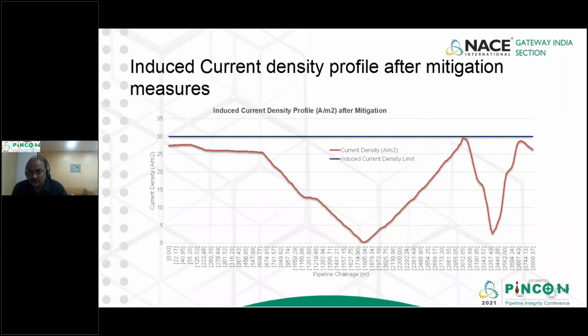So we then gave clearance for putting gas into the pipeline, because many big customers were there in this pipeline, and we were not able to commission them because we had this issue of AC current mitigation which we needed to do. Once we did this and found things were okay, we gave permission to commission the pipeline.